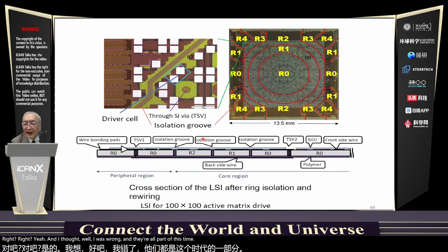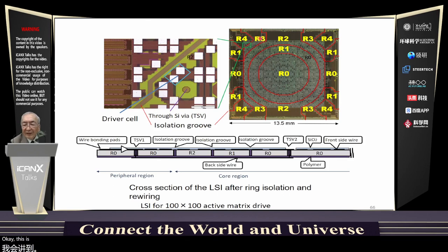Photographs of the LSI chip are shown in this slide. The arrayed driver cells are separated into 5 concentric rings to apply different offset voltages for field curvature correction, which will be explained in the next slide. This cross-section of the LSI after ring isolation and rewiring is shown on the lower part of the slide. You can see isolation grooves, through silicon vias and the backside wires to apply offset voltages to each ring.